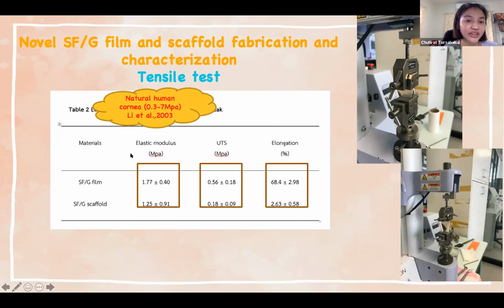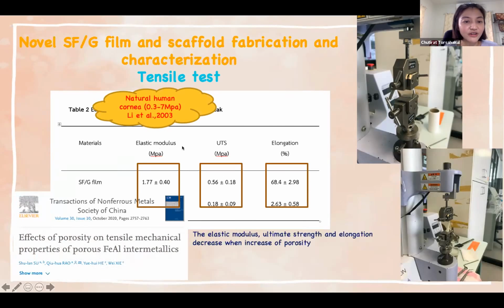The elastic modulus of my scaffold is compatible with the natural human cornea, 0.3 to 7 megapascal. And we can observe in these numbers that the elastic modulus, ultimate tensile strength, and elongation at break of the film are higher than those of the sponge-like scaffold. This is because of the porosity as well. This study said that the elastic modulus, ultimate tensile strength, and elongation at break decrease when porosity increases.